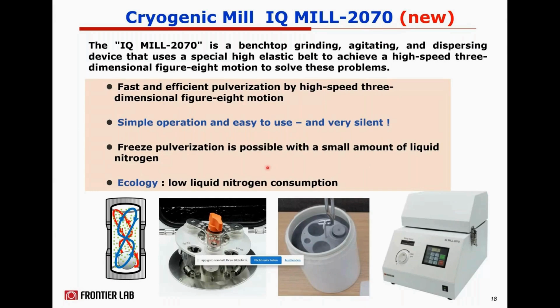Freeze pulverization is possible with a small amount of liquid nitrogen. What we do is immerse the sample, the milling vessel, and the crushing ball, everything, in liquid nitrogen for some minutes, and then we start the milling process. Also ecologically and concerning costs, it's a good thing that we have a low liquid nitrogen consumption.